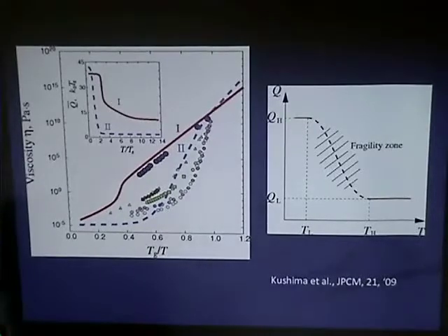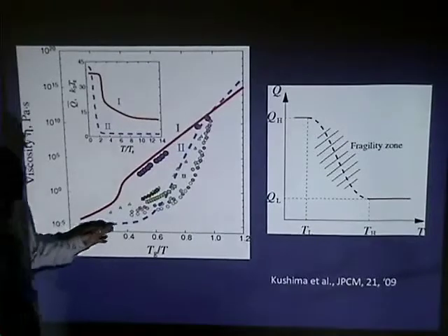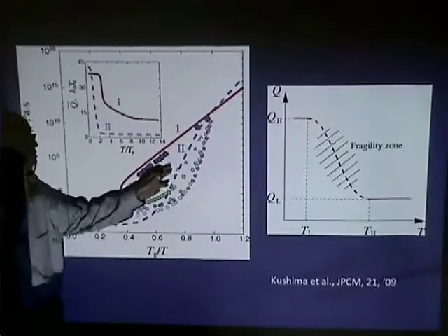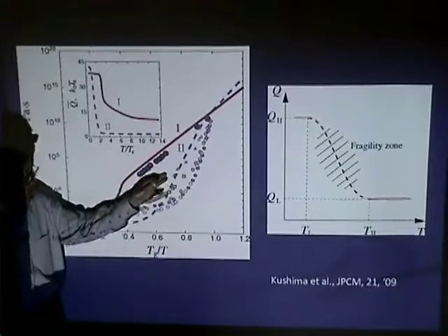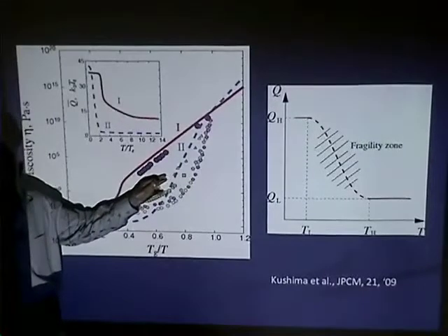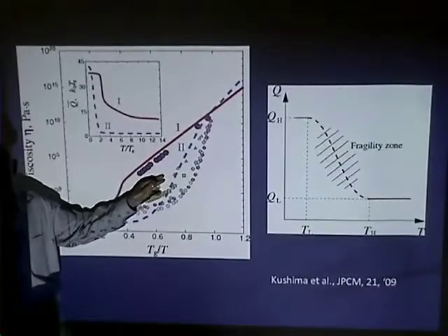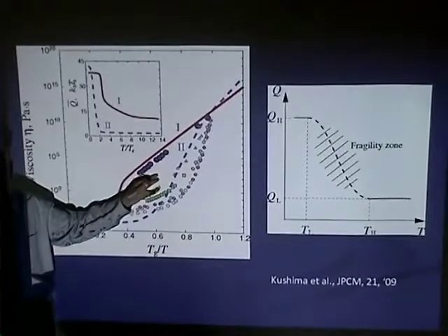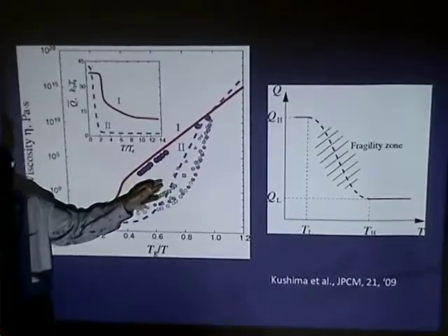Oh yes, incidentally, since you mentioned Adam Gibbs, we actually did a little more work. In this heuristic argument there was essentially just the energy, the activation energy, so there was no entropy, no configurational entropy. So we actually applied the Adam Gibbs correction.